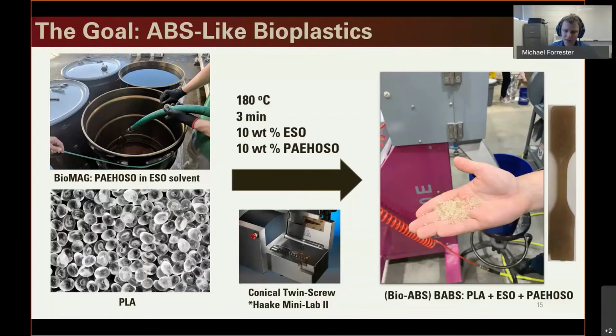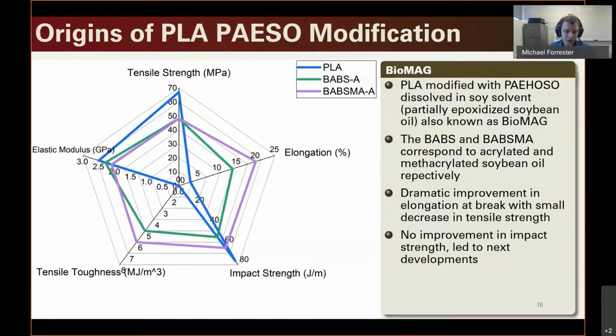And we're kind of jumping ahead a little bit, but we liked some of the results so well, we actually went up to one of the larger compounders we had on campus and made about 2 to 3 pounds of the resin to do further testing on. So getting into some of the data here, what we've found is that the incorporation of this biomag has some pretty significant impacts on the tensile properties.